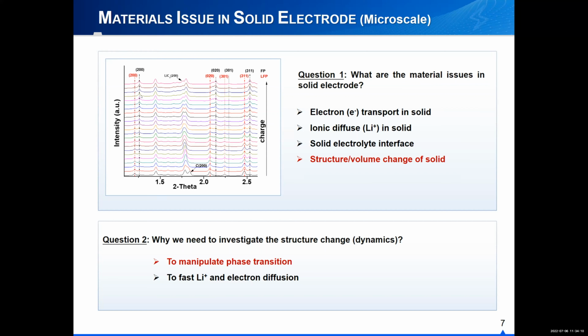So that's why when lithium iron phosphate was first introduced to the commercial market, this kind of material was regarded as not usable for fast charging. That's because the phase transition is a two-phase reaction, and a two-phase reaction is normally pretty slow. Okay, but finally, using in situ XRD, we found that when we significantly reduce the particle size of lithium iron phosphate, its phase transition behavior will change from a two-phase reaction to a solid solution reaction. So that's why lithium iron phosphate can still have a very high rate capability. Okay. So that's why it's very important to investigate the structure change.